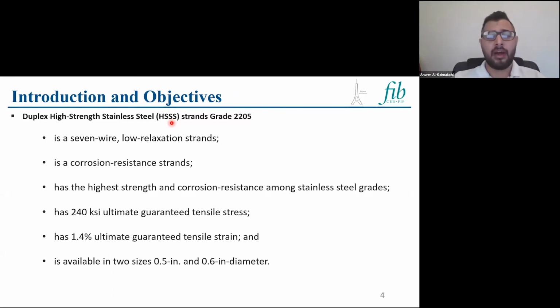It has a guaranteed ultimate tensile stress of 240 ksi, and a guaranteed ultimate tensile strain of 1.4%. The issue here is that it doesn't have as much ductility as the carbon steel strand, so special attention needs to be taken when this material is used in design. Currently, they are available in 2 sizes in the US, 0.5 inch and 0.6 inch.